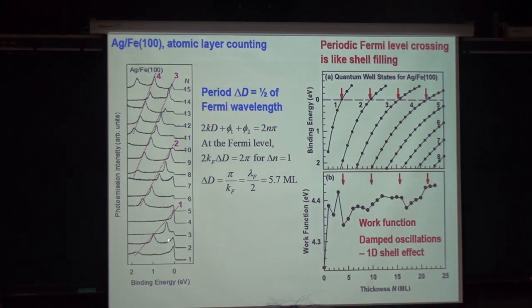Anyway, so these are the quantum well states. For a single layer, you can see there's a quantum well state, N equals 1. And we make two layers, the quantum well state is actually over here, it's not the same anymore. And then 3, 4, so the quantum well state goes through this movement and goes through the Fermi level, you don't see it. And then quantum well number 2 comes up and moves with 3 and 4.